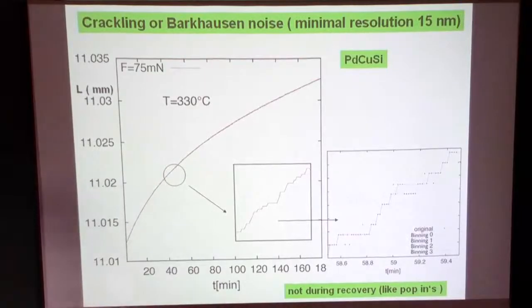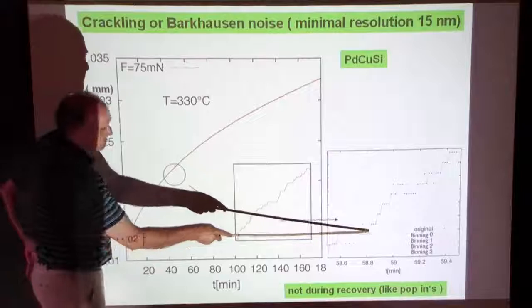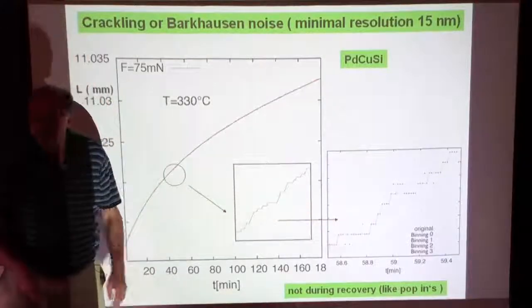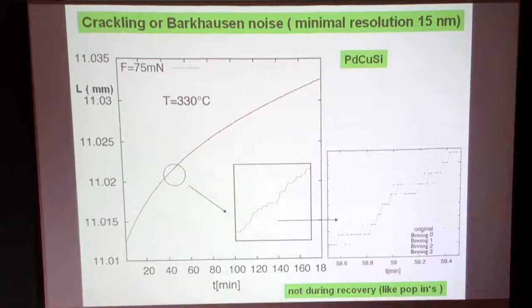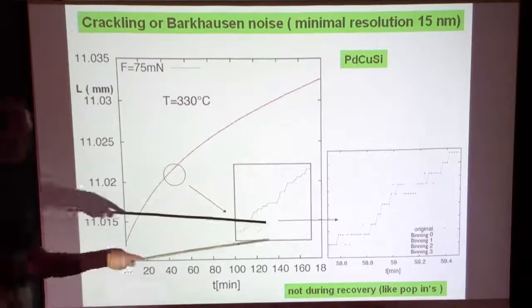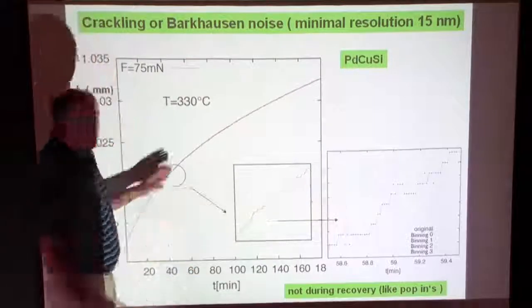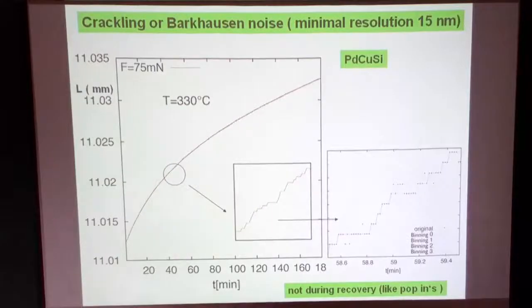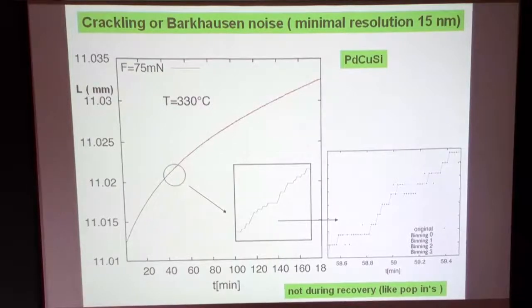But we thought, okay, if you wait for a certain time for an event and then look for the distribution of the smaller events, the one slip event, the 50 nanometer events, they will occur more often or more different. If you pull very hard in the beginning, then the system creeps and relaxes the stress, actually the internal stress, by these jumps. And so we just try to see whether this kind of waiting time analysis gives you some ideas about the power laws as well. It doesn't say that any waiting time for an event gives you the size of the slip.